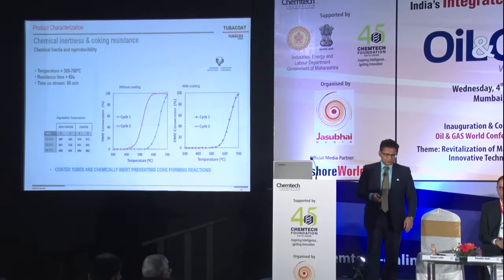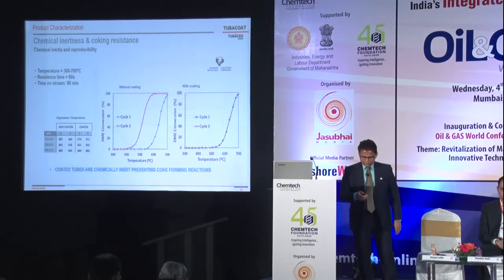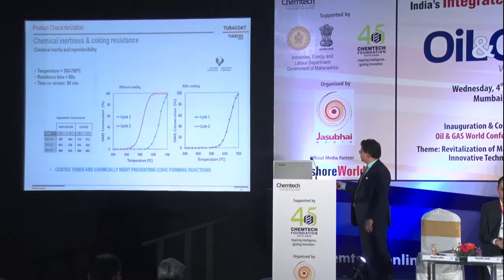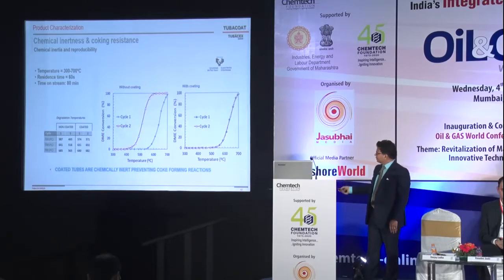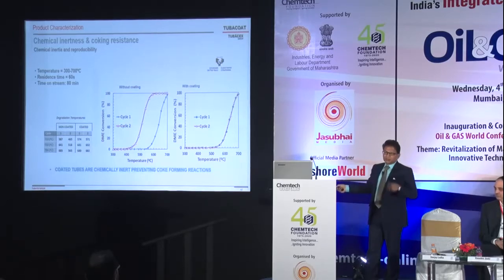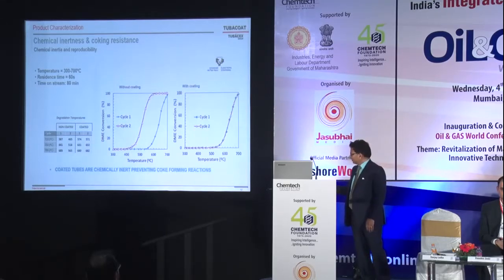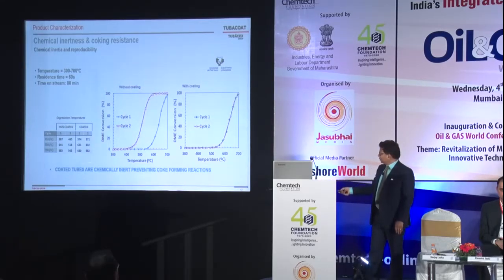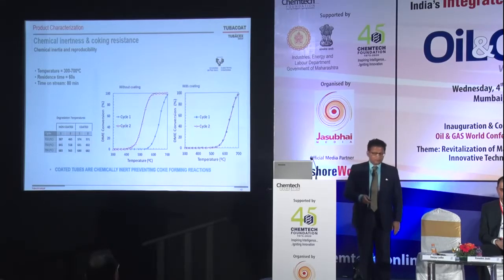So this reaction shows, without coating and with the coating, when you look at this particular chart, what you see is when you don't have a coating, you start the unit, shut down and start a second time. The second time, your activation of carbon-forming reaction for the 10% conversion is at 100 degrees earlier. So every time you shut down a delayed coker unit and start again, coke-forming reaction happens much faster. But if your tubes are coated, then there is absolutely no difference in promoting the carbon formation. It's identical because the coated tubes are chemically inert in preventing the carbon formation.